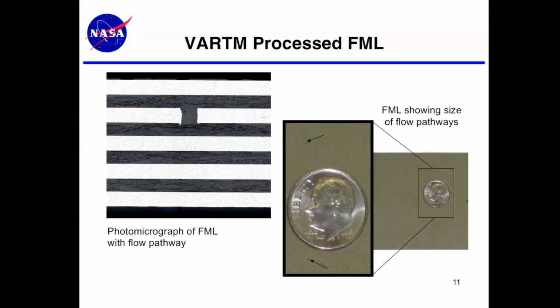So obviously the holes in the foils are flaws from a mechanical point of view, but these flow pathways, these holes, can be extremely small. You can see the photomicrograph of one of the materials. We were able to essentially get a section that showed a flow pathway or a hole, and then you can see compared to the dime on the right-hand side, these holes are extremely small. We were able to space them at about an inch apart.